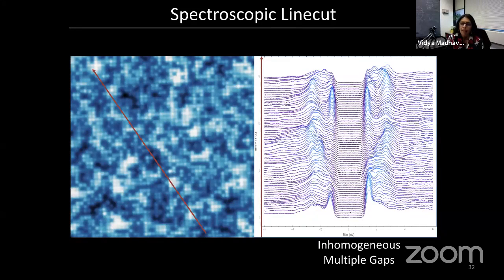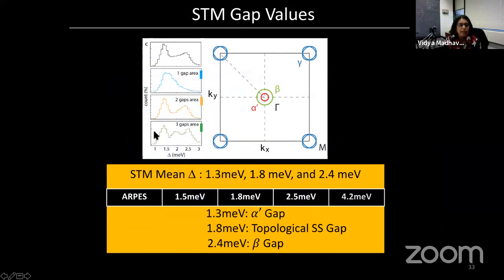Yeah, so we haven't quite been able to correlate the actual gap magnitude variation with the density of any selenium or tellurium. There's no direct correlation, but definitely there's a lot of electronic inhomogeneity, just like in the cuprates. That's why, let's just look at this histogram, even for the small gap, which is 1.3 millivolts, it's not exactly 1.3 millivolts everywhere. There's a range of gap values that you get. I see. Thanks.